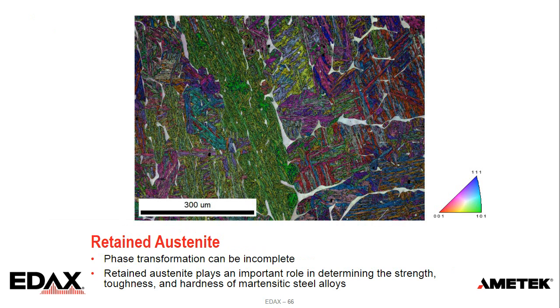That comes back to this: as we do this transformation, you can also have what's retained austenite, that not all the austenite's transformed. Retained austenite can be an important factor in determining the strength, toughness, and hardness of some alloys. And so as we go to look for this, I've sometimes called it a needle in the haystack problem. We want to look at a large area, but we want to look at a fine step size. And that's where some of these faster, velocity CMOS type cameras are really useful. We can look at larger areas with finer step sizes.